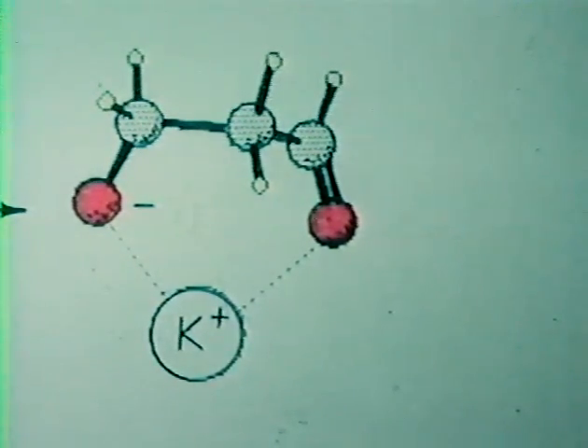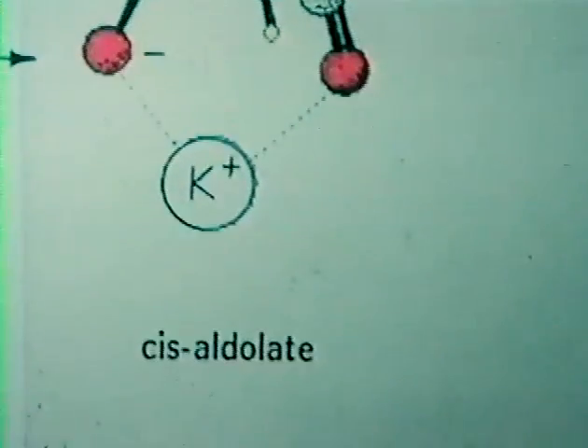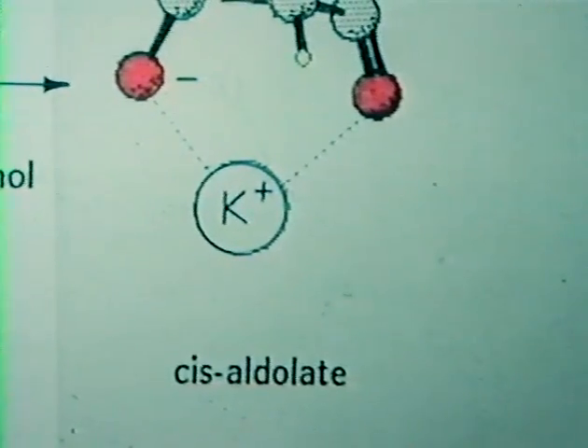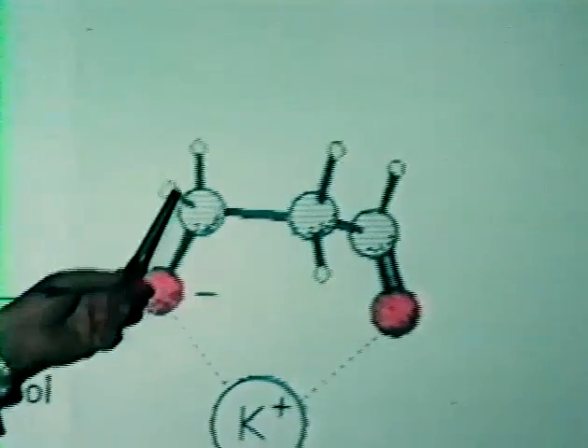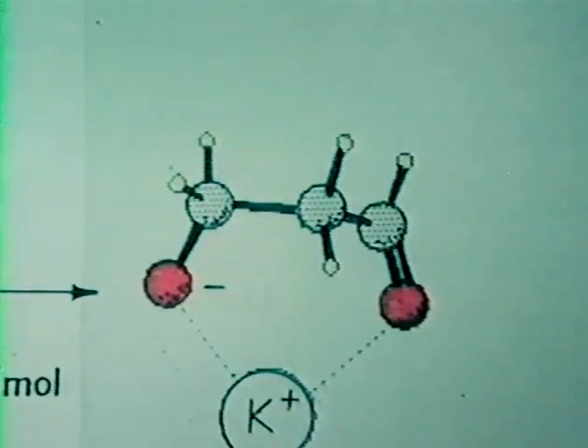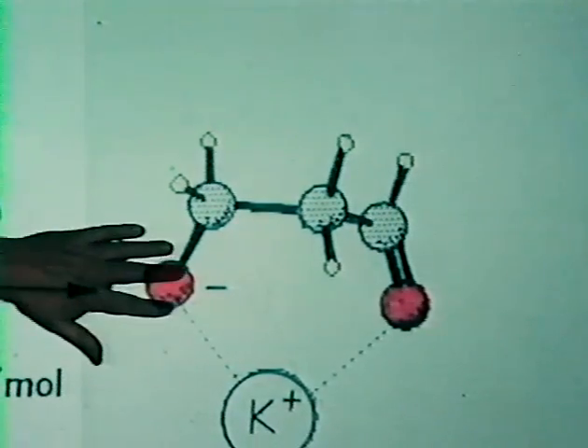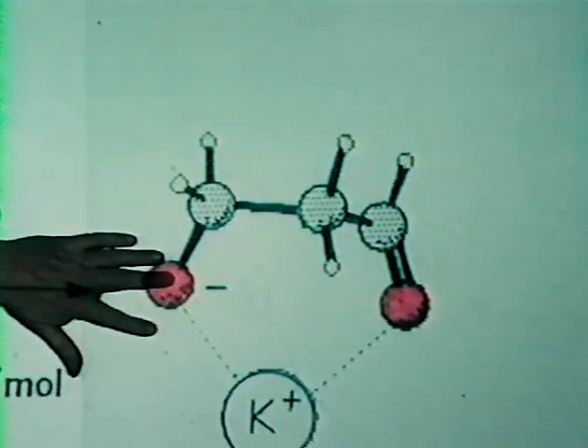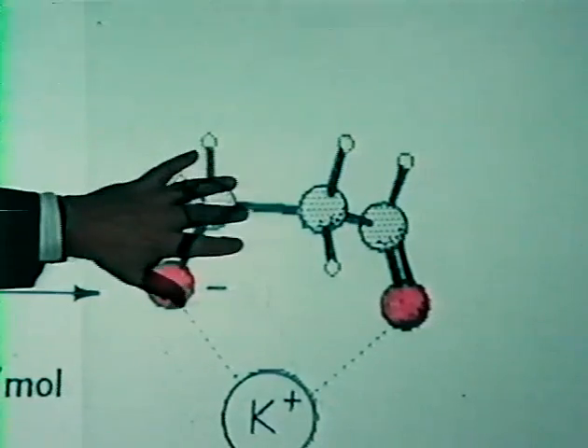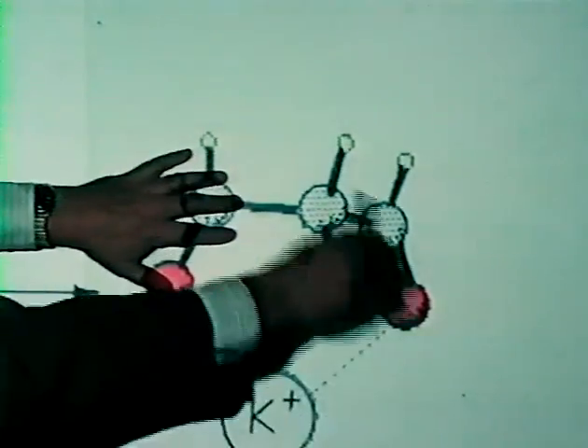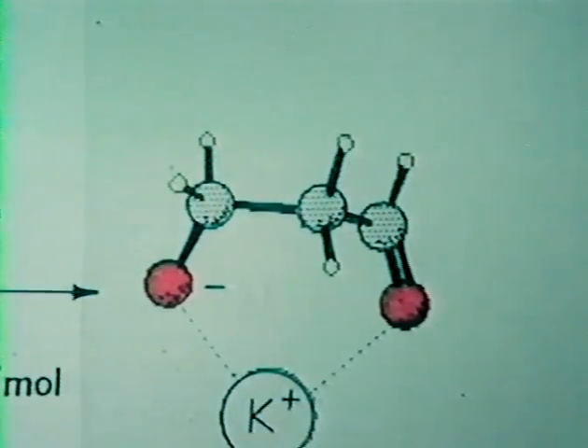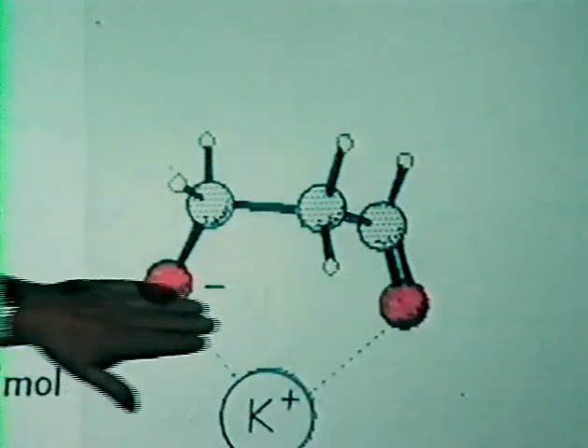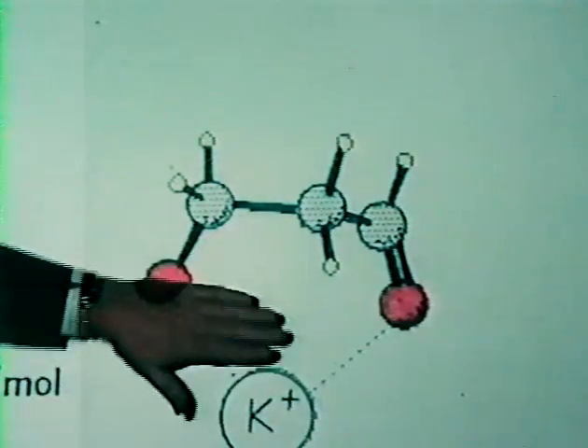What we get is a 1,3 keto alkoxide that is bonded to the alcohol. I called it cis aldolate. I'm sure that this is not IUPAC terminology, but this is what you would expect as a first step in the aldol synthesis. But then what you expect is that this oxygen picks up a proton somewhere, loses water, and this gets hydrogenated to linear propanol, but then the label would remain here. What happens instead in our system is that there's an isomerization.